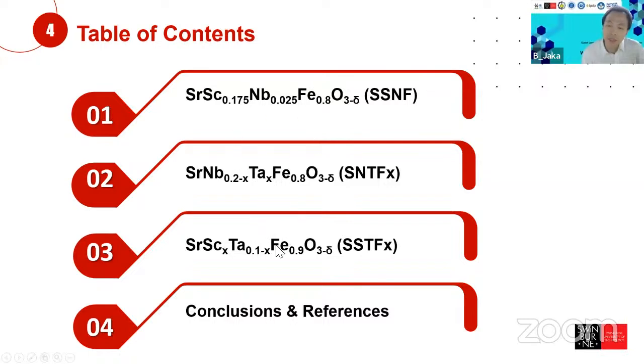The other things besides the similarity, or the integral aspects of these three materials, besides the co-doping, meaning we put two different dopants into the B site. In here, as you can see, in the B site we only have iron, so there is no cobalt at all in the perovskite lattice. Our group and collaborators departed away from cobalt, because cobalt is more easily thermally reduced at high temperature.